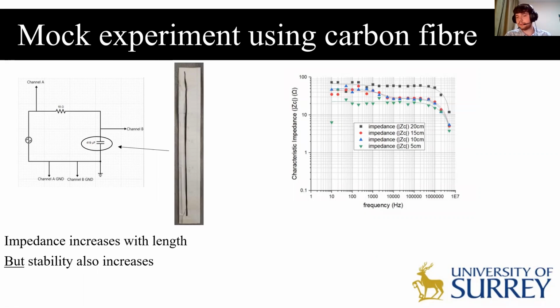What was found, and what was expected, was that the impedance of the wire increased with the length of it, which is shown on a graph. But what was more surprising and useful for the future experiments was that the stability of impedance actually increased with the length as well. So the length of wire now becomes a benefit as the impedance response became more stable.